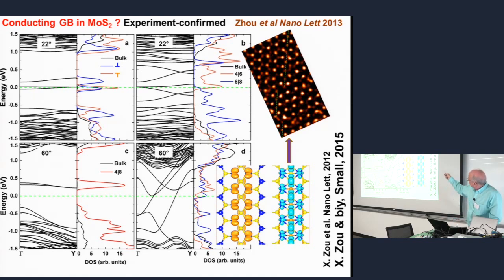So, grain boundaries in this case. I just show you without much of explanation. You can have grain boundaries, and the interesting thing is that every time you get different band structure. Grain boundary is one-dimensional object, right? It's kind of translational invariant in one direction. It has a band structure. And interesting, just one to single out, is that some of them are metallic. That's quite exciting, we thought, because it means that embedded into semiconductor material, you can have one-dimensional metallic thread, right? This is one-dimensional nanowire, if you wish, built in, just because of the grain boundary.